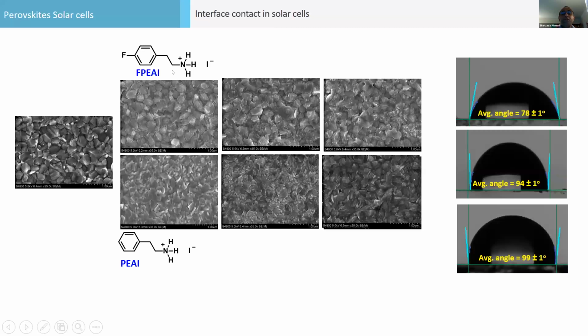On top of it, we deposit the FPEAI molecule in different concentration. The surface changes, you can see differently. And in case of PEAI, you can see the crystals are not like that, but it forms a lamellar type of structure. But the significant change you will see is here. This was the aim, to make the surface more hydrophobic. The pristine mixed perovskite gives you a contact angle of 78, with the PEAI molecule it is 94, and with the fluorinated it is 99 degrees. So the surface became more and more hydrophobic, an ultra hydrophobic surface.